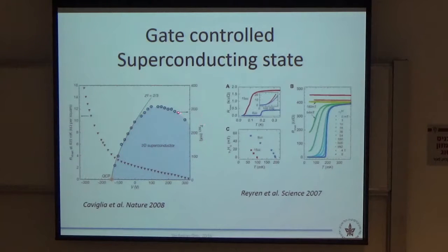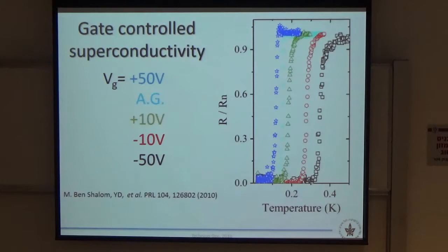But Tc is 300 millikelvin, not 100 Kelvin. So Tc is lower, but it can be controlled very efficiently in a continuous fashion. If you want to look at Tc versus doping, usually you have to grow many samples with various dopings, but here you can study the phase diagram in a continuous way. Okay, now we don't want to look at superconductivity.